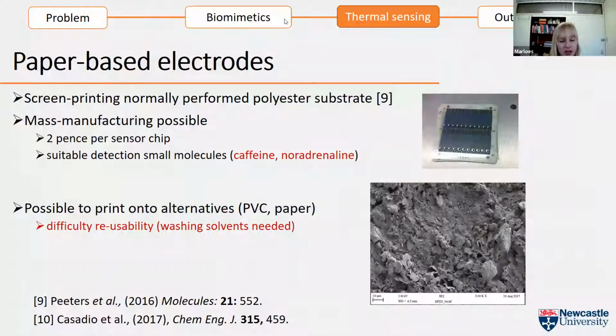Now, if you want to think of a more sustainable aspect, this is what these screen printed electrodes look like. On the top, you can print lots of them, so they can give me more electrodes than I can normally measure. And under the scanning electron microscope, you can see that this is a very rough surface. But normally they are printed onto polyester substrate. So in a way, you have more plastic on what it's printed on than the little black dot, which is actually the carbon electrode itself.